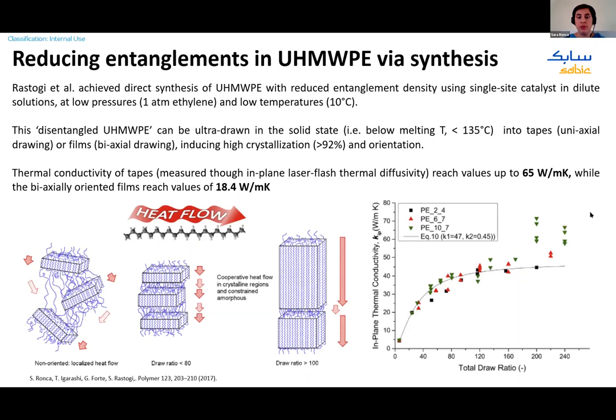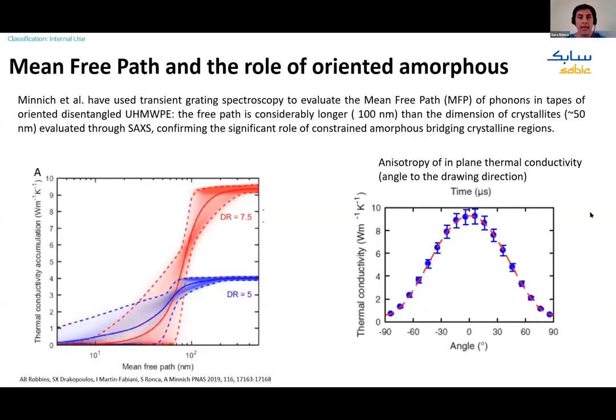And it's very interesting to realize that even the biaxial orientation could induce high thermal conductivity, and the films were showing an in-plane thermal conductivity of 18.4 watt per meter Kelvin, so in the range of steel.